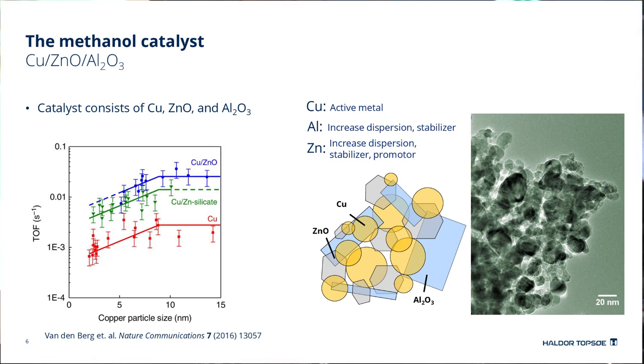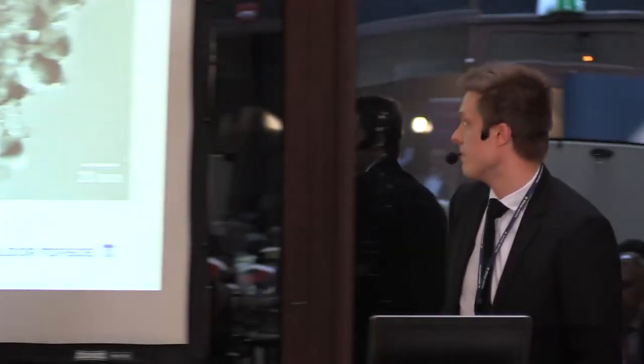This is very well seen from this picture here, where on the y-axis you have the turnover frequency of methanol. This is an intrinsic measure of how many molecules of methanol are produced per active site in the catalyst. And what you can see here is if you go from a pure copper system to a system where you have zinc oxide, then you significantly boost your methanol activity. I'll emphasize that this is on a log scale.